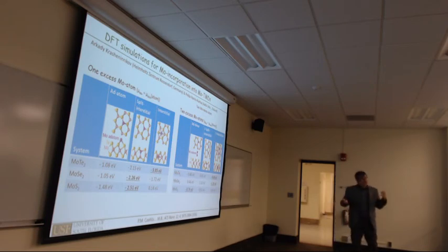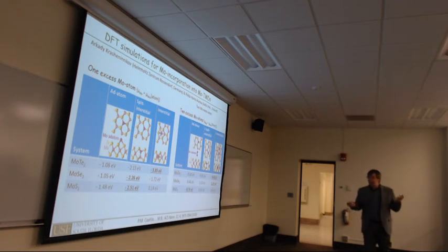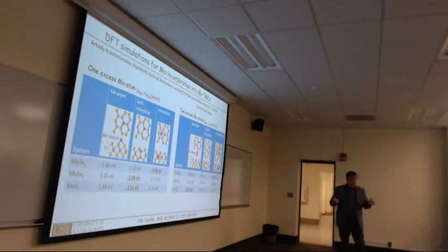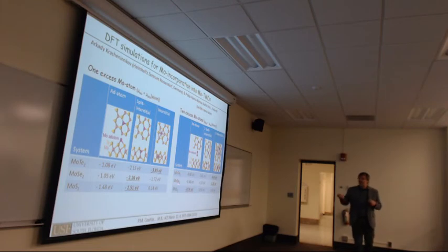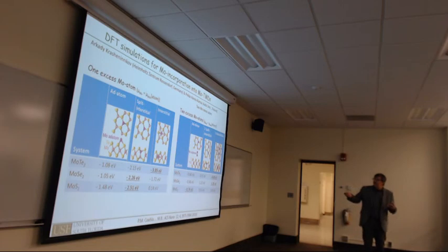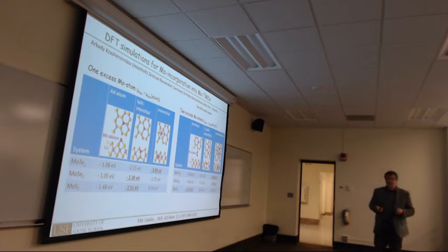So that seems to be in agreement with the experiments that show that on molysulfide you do not form these twin grain boundaries, but you form clusters on the surface, while for molytelluride and molyselenide you can form twin grain boundaries, whereas these 2 interstitials may be the first step of the nucleation and growth of these grain boundary loops.